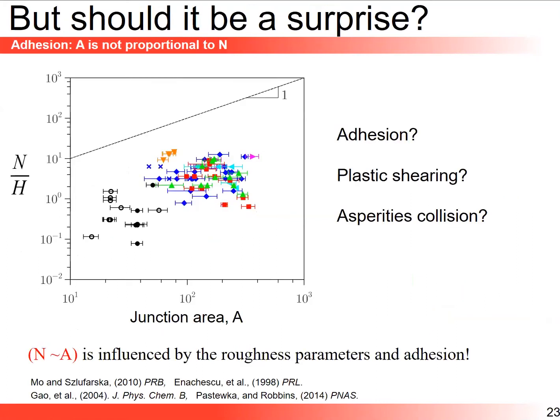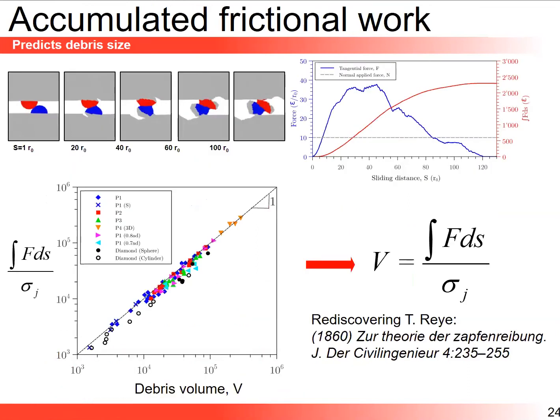And the reason is actually very simple. At the core of Archard's model is the assumption that the contact area is proportional to N, but it's not for us. And the main reason, and that's well understood in the community, is that we have adhesion. We're looking at adhesive wear at a small scale. And because you have adhesion, you can form a non-zero contact area for zero applied load N. Okay? So you see, we don't have this proportionality between those two quantities. What worked well, however, in order to predict the final debris volume is the accumulated frictional work. So here I'm showing you some snapshots of the formation of a debris. And in blue, you have, as a function of time, the tangential force.